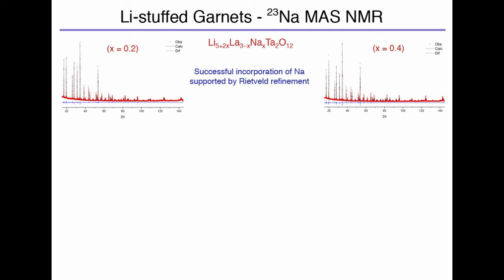So the first thing was to make the materials. We made them and we found that we had a solubility issue. The maximum amount of sodium we could get into this structure was 0.4. Everything else, it wasn't produced, it would make side reactions, it would pull out the starting reagents, a whole load of things, so it just didn't work. So we could only get 0.2 and 0.4 to go into the system. But using Rietveld refinement, which is looking at the long-range diffraction structure, we confirmed that we had sodium in there.